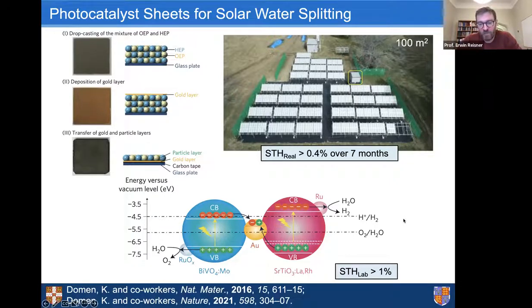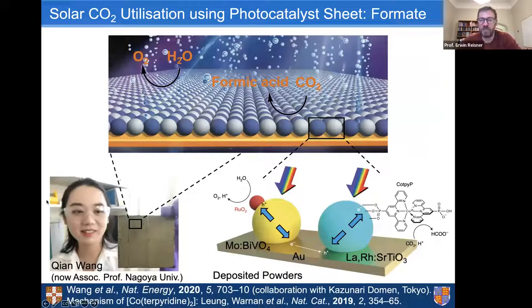So the main difference between this system and the leaves is that in this case, we produce both products, hydrogen and oxygen, in very close proximity. That's a disadvantage because when we produce knallgas, hydrogen and oxygen together, it is dangerous, and it also needs to be separated by a membrane. On the other hand, this also offers a significant advantage because we are avoiding significant pH gradients, because now water oxidation that releases protons and proton consumption for proton reduction are very close together. So in a localized environment, we avoid the buildup of pH gradients that are an issue and something of concern for the artificial leaves.